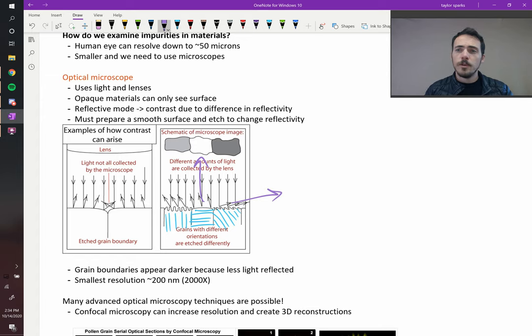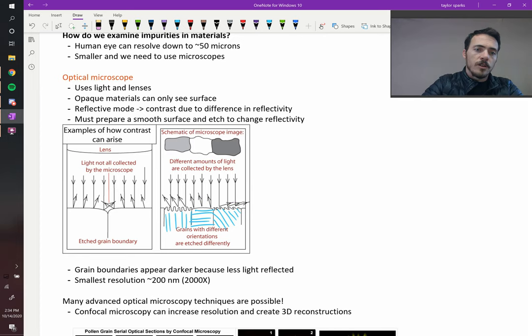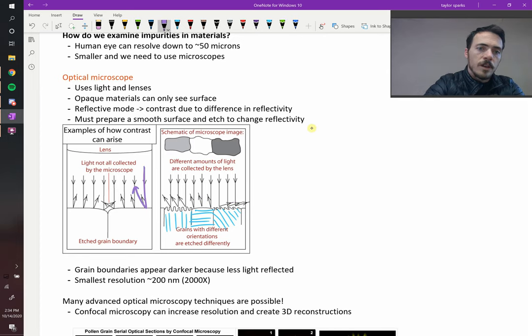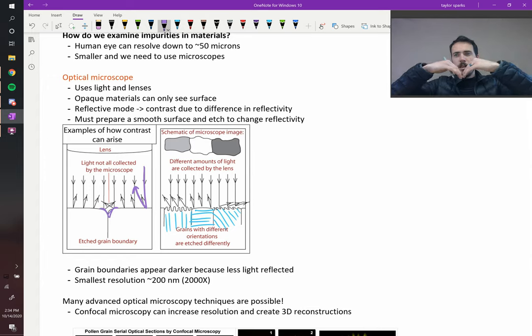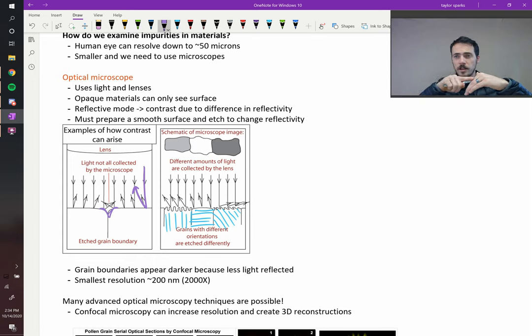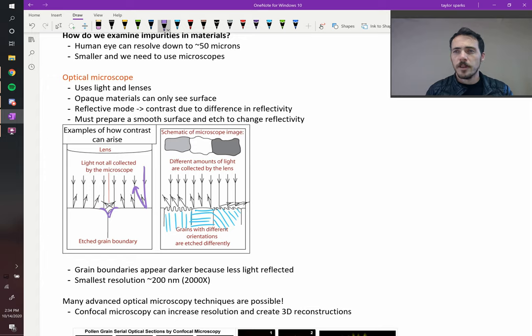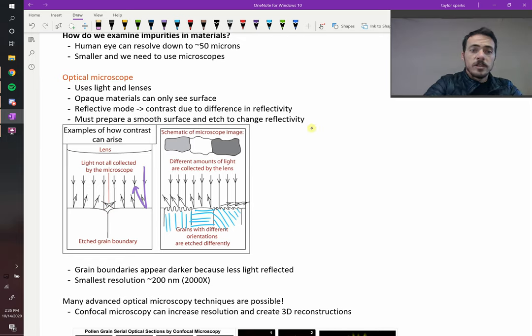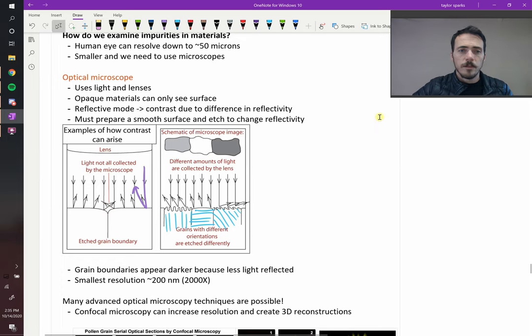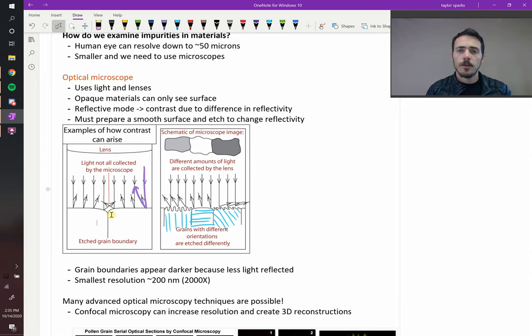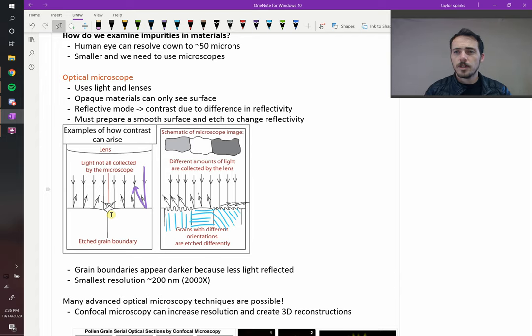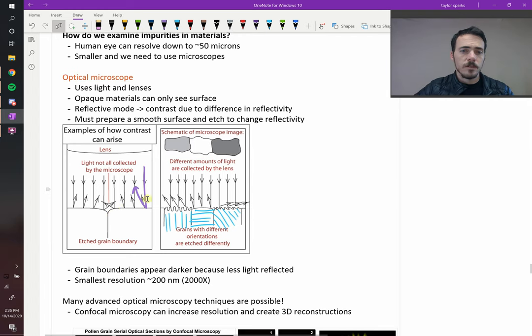Oftentimes we want to see these grains, because we want to know how big the grains are, because that influences things like mechanical and other properties. So something that we'll often do is we will intentionally make it so that these grain boundaries reflect light differently. That's what you see here on the picture on the left. Normal light is coming in and doing its thing, but if you've done something in the grain boundary, like etch it so it has this sort of pit, then when light comes in, most of the light will get caught in that pit, and it won't escape, or it'll bounce out, but not back to the lens. So these will appear darker. Grain boundaries often have these pits, and so they show up darker. You see a big dark spot instead of a grain boundary, which is nice. So how do you make a pit? Well, you can etch it chemically. You can put it in acid, for example, a dilute acid for a while that can etch it, or you can thermally etch it. If you heat it up to a higher temperature, it will form these grooves.